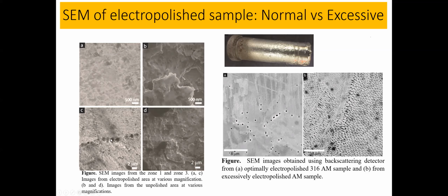Panel C is a little bit zoomed out version. If you start coming out, you can see the scale. It is a 2 micrometer scale. You can see a lot of features present on the surface. It tells you about the microstructure of the AM parts, which appears once you do surface cleaning. But if you do not do that, you still see a lot of hills and valleys, very rough surfaces. Now I'm on the right side figure.